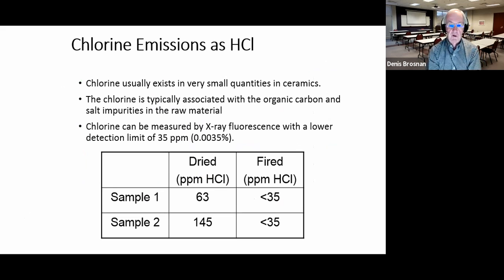Chlorine emissions are a little bit different. Chlorine is typically not in the crystal structure of a ceramic material. It certainly can be in the binders or in the carbonaceous phase that might be entrained in the kiln. It certainly can be in some of the fuels that you use. So nevertheless, we can detect that pretty easily by X-ray fluorescence. Lower detection limit is about 35 parts per million.